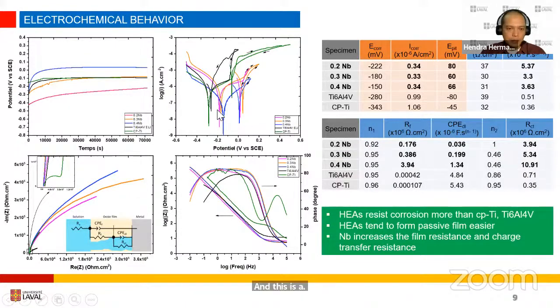And this is the electrochemical behavior of our alloys. We can reach a stable open circuit potential after a very long time, so it's after 6 hours minimum. So we are sure that we have some stability, except for the pink one, which is the high entropy alloy with the lowest niobium content. And then we continue with cyclic polarization to check how it behaves, whether there is passivation. This is actually the polarization curve. We scan the potential from low to high, and after that we return the potential from high to low, so it's cyclic, making a loop.